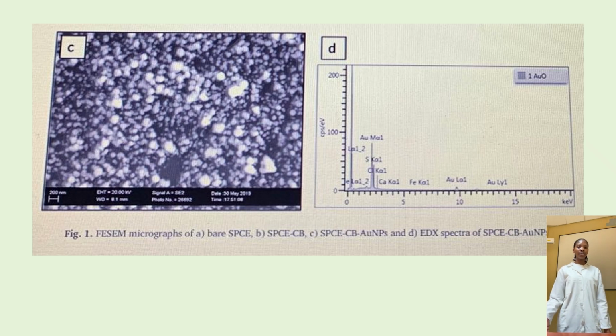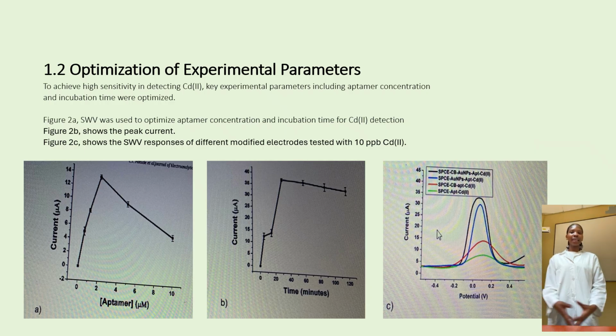These are nano-gold particles, which shows that the gold was successfully deposited. Furthermore, the EDX spectra was used to confirm the deposition of the gold, as you can see in figure D. Secondly, we have the optimization of experimental parameters. To achieve high sensitivity in detecting cadmium, key experimental parameters including aptamer concentration and incubation time were optimized.